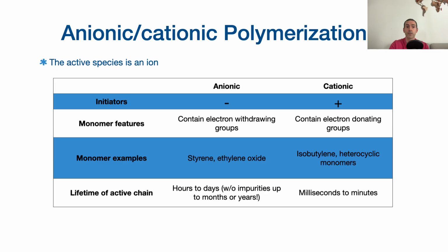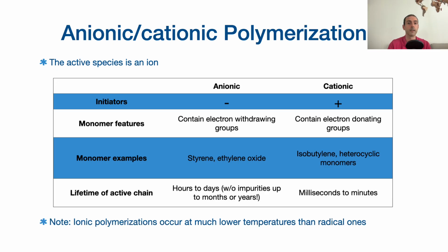Whereas in cationic polymerization, the active centers live much less. Carbocations are far less stable than carbanions and undergo rapid side reactions. So, the lifetime of their chains is much shorter. Given the big difference in chain lifetime, we can expect significant differences in terms of chain length distribution of polymers synthesized with the different techniques, right? Radical, anionic, cationic, but this is yet again another story.